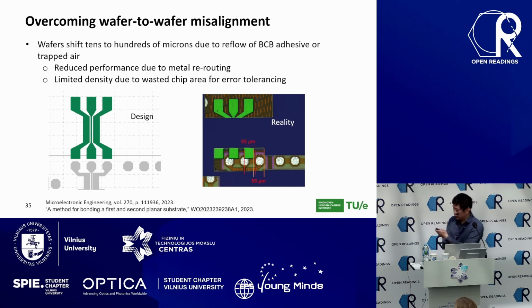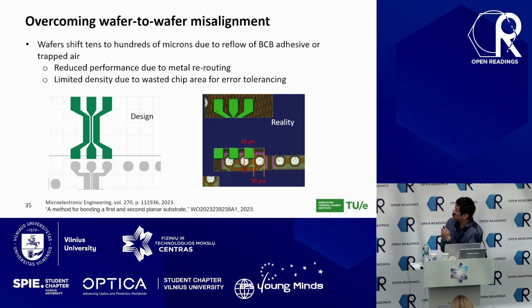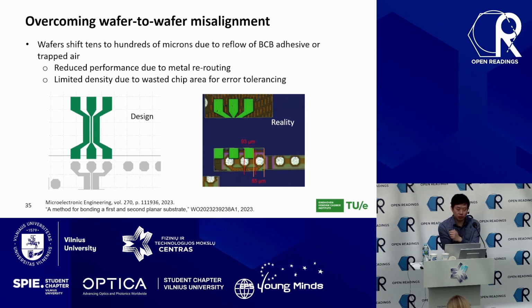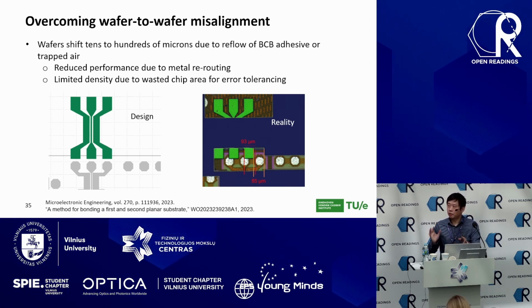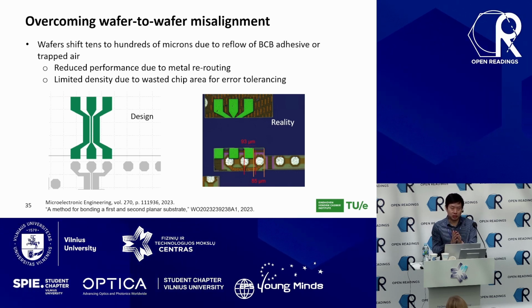Of course, like I hinted, it's a bumpy road. To achieve that, there are several technical challenges we are facing. First of all, I'm not sure how many of you have handled a semiconductor wafer. They're typically shiny, right? Otherwise, something is wrong. Those shiny wafers tend to drift with each other when you put them close to each other. And they also tend to trap air in this very thin interface. And in our particular case, they can lead to a relative shift between the two wafers.